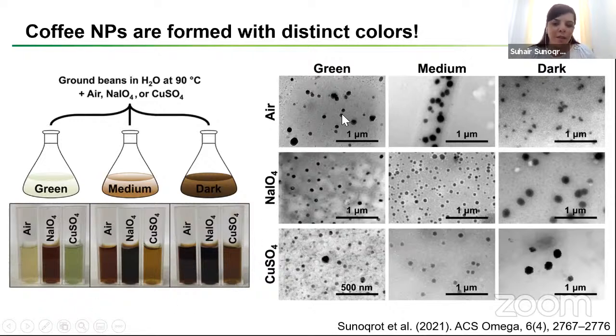And when we looked at them under the TEM, we also found that they are actually nanoparticles. So even just by the presence of air as an oxidizing agent, the polyphenols in the aqueous coffee extracts can form these nanoparticles. But the polydispersity was rather high. So using the oxidizing agents resulted in more uniform nanoparticles, especially for the medium and dark coffee extracts. We think because the roasting process already makes the coffee components turn into polymeric materials, which can help in forming these nanoparticles.